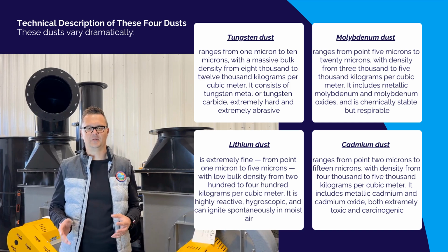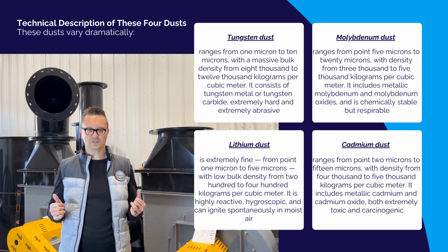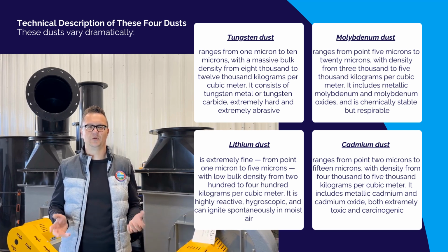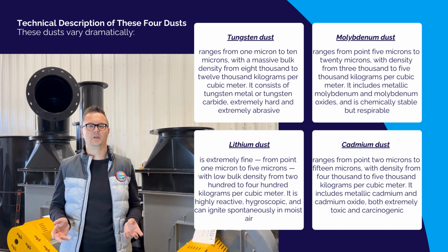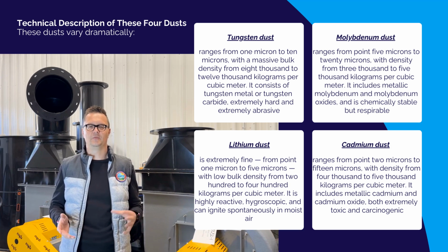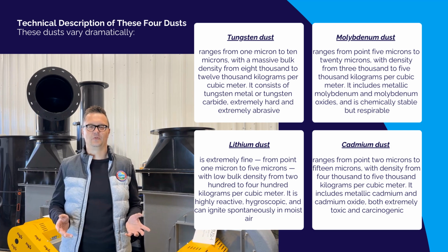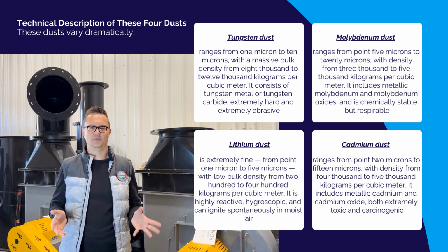Second, molybdenum dust ranges from 0.5 microns to 20 microns, with density from 3,000 to 5,000 kilograms per cubic meter. It includes metallic molybdenum and molybdenum oxides, and is chemically stable but respirable. Third, lithium dust is extremely fine, from 0.1 micron to 5 microns, with low bulk density from 200 to 400 kilograms per cubic meter. It is highly reactive, hygroscopic, and can ignite spontaneously in moist air.